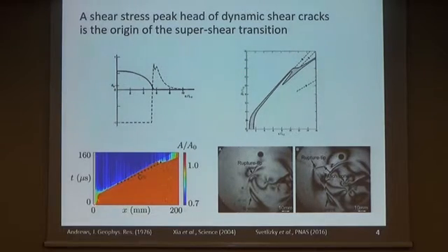You have an initial crack that is starting here, some slow nucleation, propagation going on. The cohesive zone is very small and you cannot really see it in this area here. But at the same time, with this information from the numerics, we were able in the experiments to track this little bump. And these are the black dots. We could measure its shear wave speed, and then here you see the daughter crack that is propagating. So this is very new results that closes the gap of the missing bump that wasn't able to be observed with this methodology. Okay, this is just as a little side.